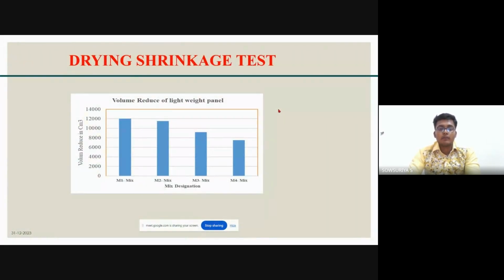Now we're going to see the testing analysis. There are 5 tests we did: a drying shrinkage test, fire resistance test, density test, water absorption test, and the compression test. In the drying shrinkage test, the volume of the lightweight panel reduced from 12,000 cubic centimeters to 7,000 cubic centimeters. This is for mix 1, mix 2, mix 3, and mix 4.